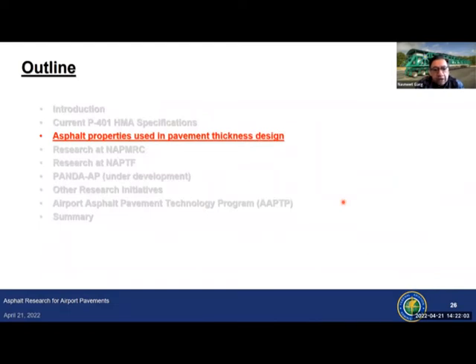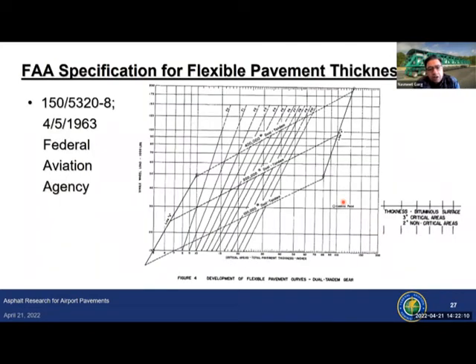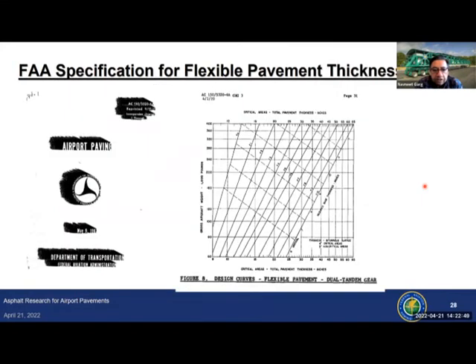Next, I'll talk about what asphalt properties are used in pavement thickness design over the years as the design procedure evolved. So what you see on this slide is a nomograph, because previous to 1994, all pavement thickness designs were done using nomographs given in Advisory Circular 150/5320. This version was released in 1963. And what you see is the pavement thickness design was a function of the landing gear, the type of subgrade soil you had, and the wheel loads. For asphalt, they provided a thickness of 3 inches for critical areas and 2 inches for non-critical areas. And they had these charts for different landing gear configurations.